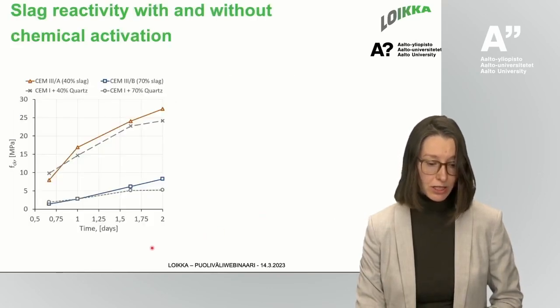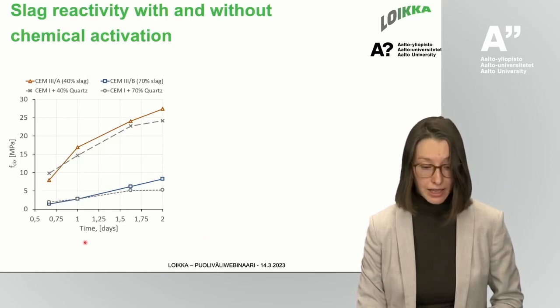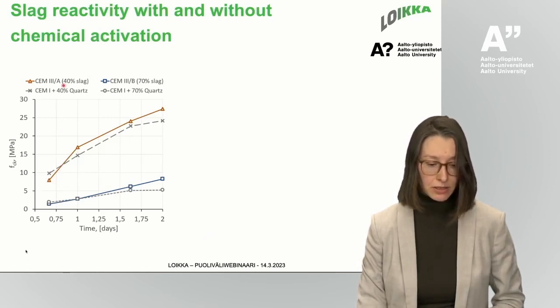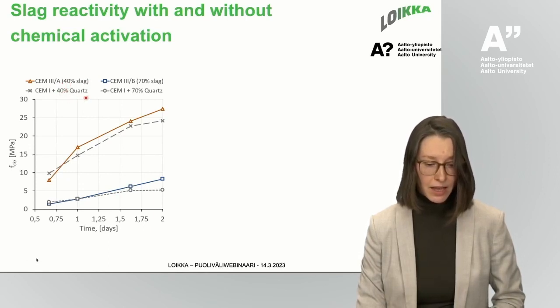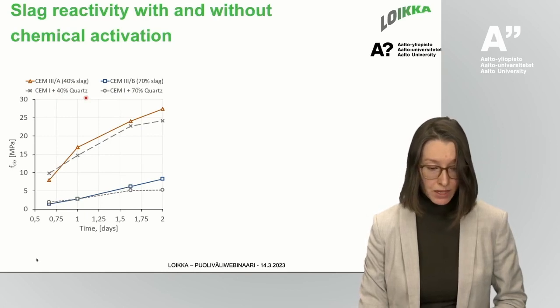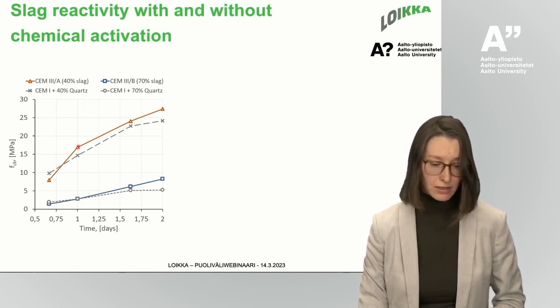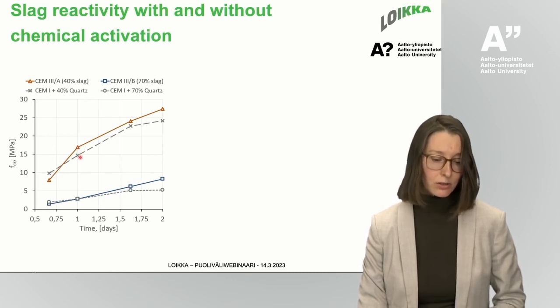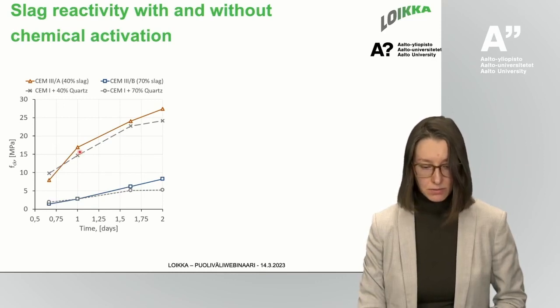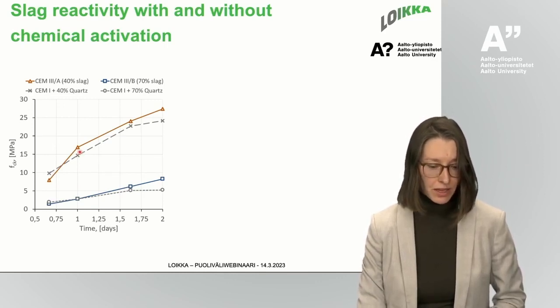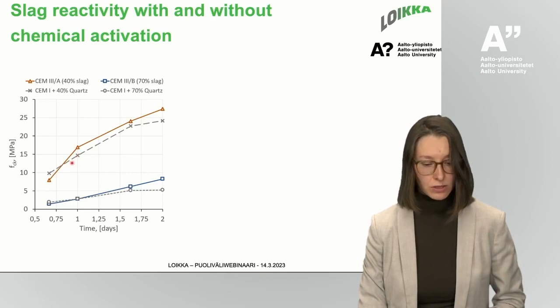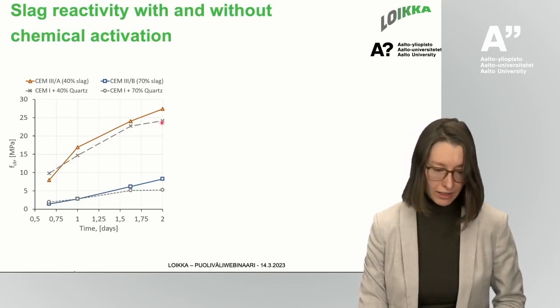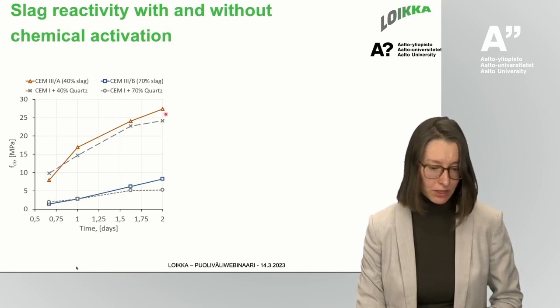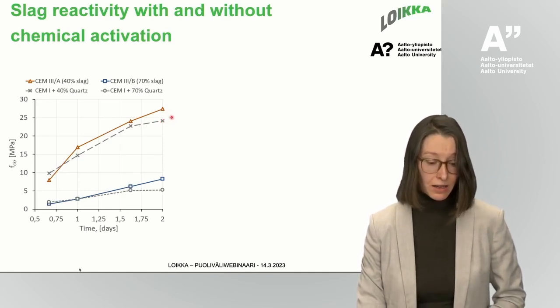First, we decided to check the reactivity of slag. We replaced the equivalent amount of slag with an inert material, in our case quartz, and checked the strength development. As you can see, slag started to react slightly already in 24 hours, which shows us that something happened, and since there is no compressive strength gain in inert material, we can assume that slag reacts.